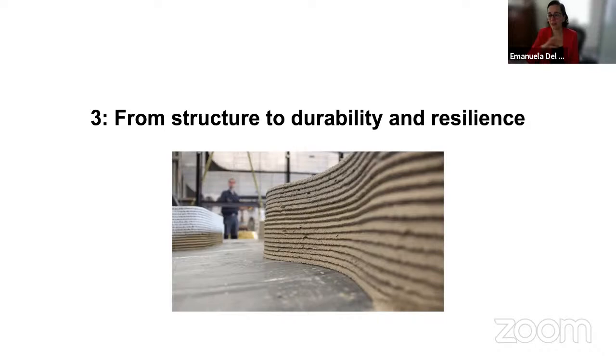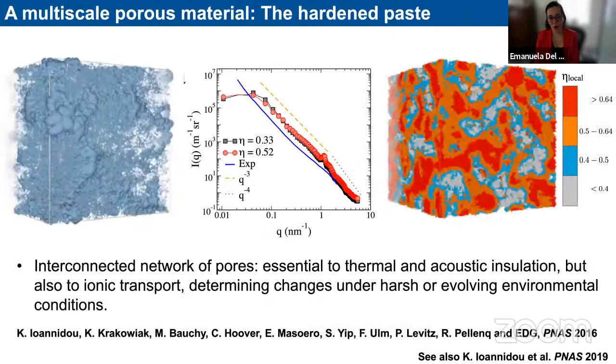And so with the type of simulation that I showed you, basically you can start from the nanoscale forces, you can go into the gel formation, and then if you push the densification of the gel up to the very late stages, you end up with this type of computational sample that we have generated in the computer, which here is colored using the local density. So you can see that you get your little cube of material that is very dense locally, but it's still fairly heterogeneous, and it has features, these large pores that are elongated and quite rough on their surfaces due to the non-equilibrium nature of the process that leads to this solidification.